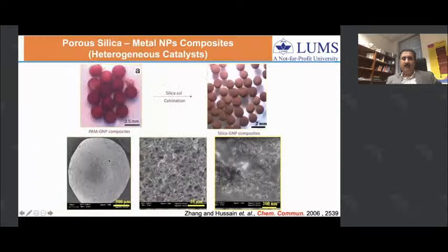We further extended this work to develop a generic strategy to produce heterogeneous catalyst again. In this case, we have polymer gold nanoparticle composites. It is still highly porous, and you can infiltrate a variety of inorganic sols into this—in this case silica sol, but you can equally use silica, titania, zirconia, or aluminium sol. Once you have this composite, you can calcinate to have these gold particles on silica, in this case, silica matrix.